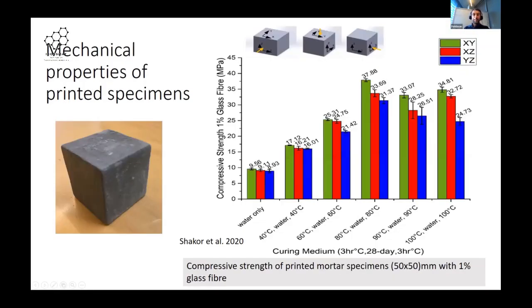Glass fiber is usually used as a reinforcing material, which helps to improve the mechanical properties as well. Here we can see, especially in compressive testing, we got about 37 megapascal. We tested a similar cube without glass fiber and got around 25 megapascal, especially in this plane, the XY direction, because all these materials, when printed, have orthotropic properties.